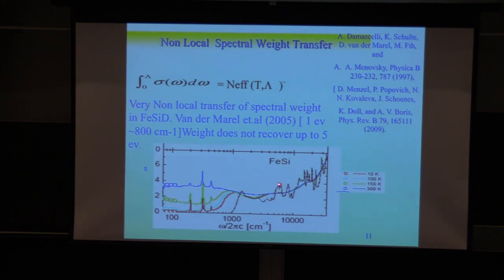And here's an example. This is a material which undergoes a metal insulator transition. You measure this thing up to very high energies, up to 1 eV or up to 5 eV, and you see that as a function of temperature, this integral changes with temperature. So that's very, very unusual. And it falls outside the simple band theory models of solid state physics, and it's very difficult to explain with the quantum framework.